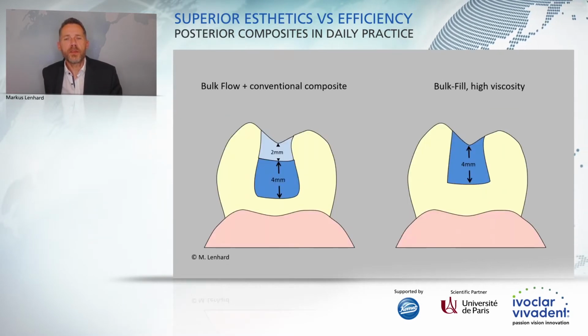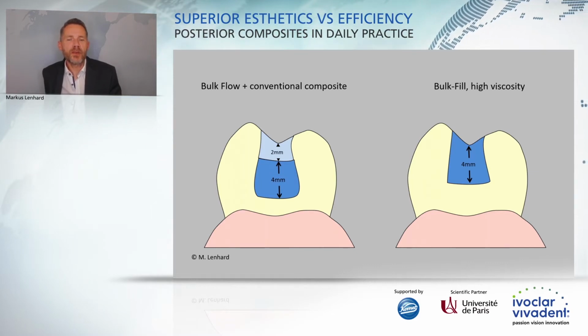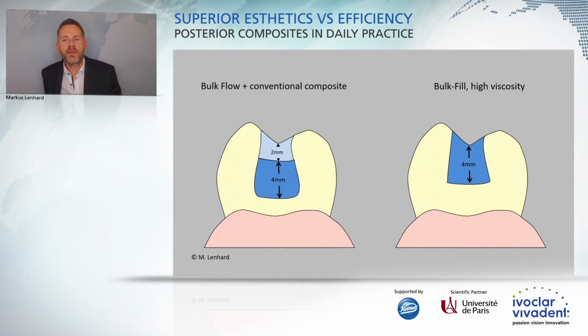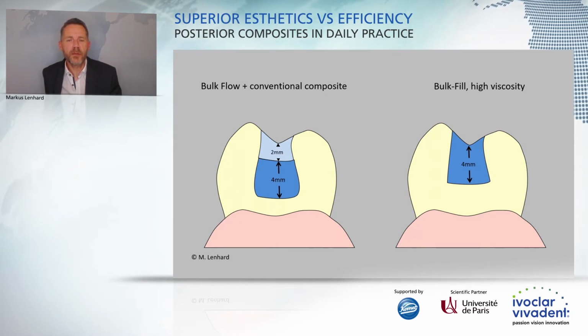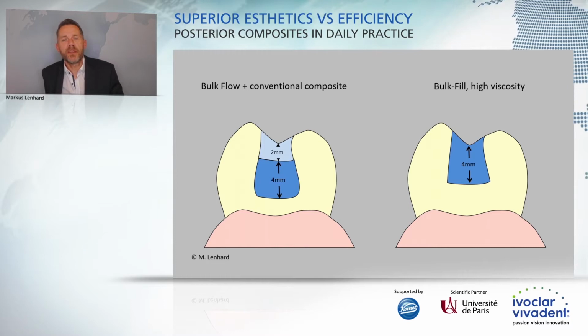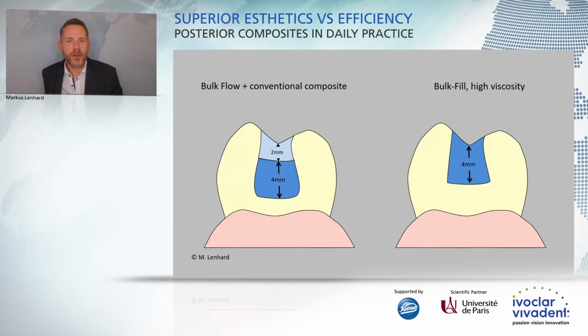So when we look at the flowables today in the market, they were first introduced as a bulk fill, flowable bulk fill, because of their lower filler load. You had to cover them with a more stable conventional material to guarantee stability of the restoration. Shortly after the introduction, we had then the introduction of the high viscosity bulk fill materials. So they had a higher filler load, a higher flexural strength, and you could layer them still in 4 mm layer thickness, but right up to the occlusal surface, they were stable enough to withstand occlusal loading.